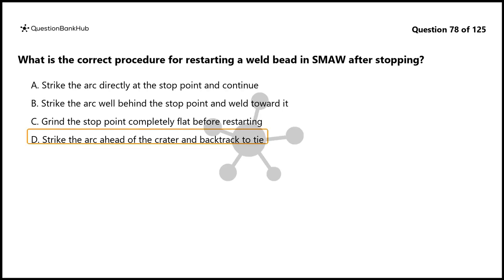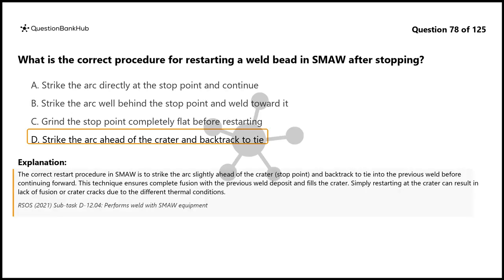The correct answer is D. Strike the arc ahead of the crater and backtrack to tie. The correct restart procedure in SMAW is to strike the arc slightly ahead of the crater, the stop point, and backtrack to tie into the previous weld before continuing forward. This technique ensures complete fusion with the previous weld deposit and fills the crater. Simply restarting at the crater can result in lack of fusion or crater cracks due to the different thermal conditions.